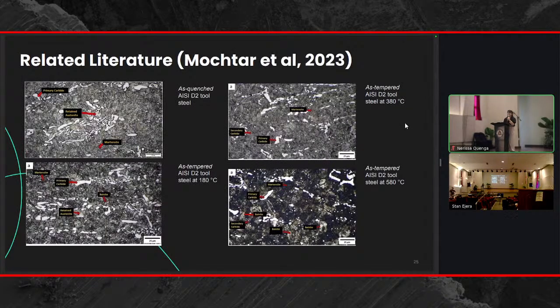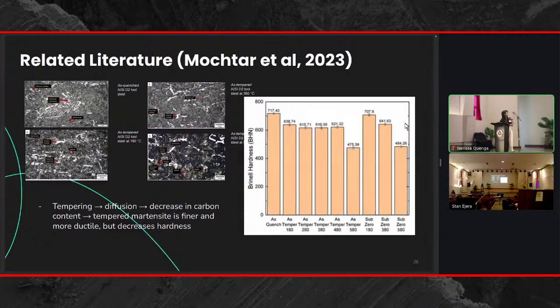Moving on to discussion, a key point in our analysis of the metallographic structure is the microstructural evolution of AISI D2 steels as they're tempered. After quenching, as tempering temperature increases, we see the decrease of retained austenite and an increase of fractions of tempered martensite and coarse carbides, indicated here by the precipitation of large angular carbide structures in the grain boundary network. Generally, as in literature, the hardness of AISI D2 steel tends to decrease as the tempering temperature increases, because as we recall, the reason why martensite is hard in the first place is that as it forms, carbon is trapped inside the martensitic structure, which increases hardness.